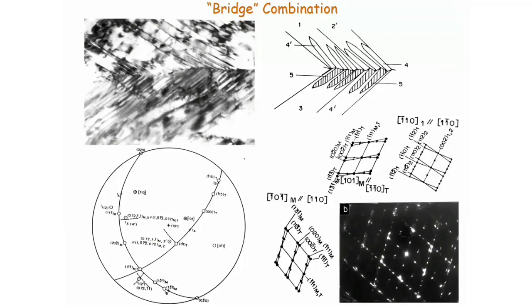And the only additional point I will say is that if there were no restrictions and there were irreversibility, you wouldn't have had the reverse transformation happening at 80 degrees. It's very difficult to think that you can have the parent phase coming out at 80 degrees. You would have to have a much higher driving force, and you have to go to much higher temperatures to get the austenite of several orientations, because they're forming fresh grains. So those alloys which show martensite which is irreversible have a larger hysteresis. Here this hysteresis is small. That's one more characteristic of the shape memory alloy.